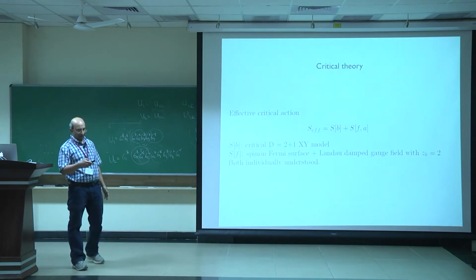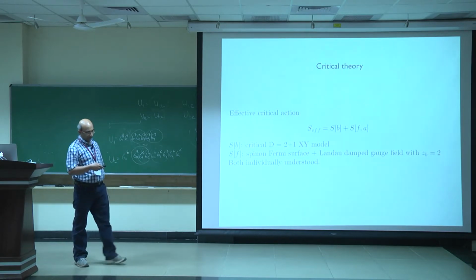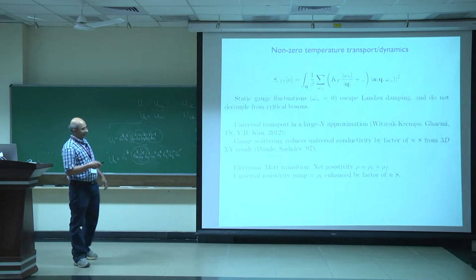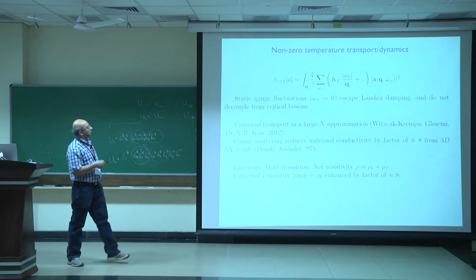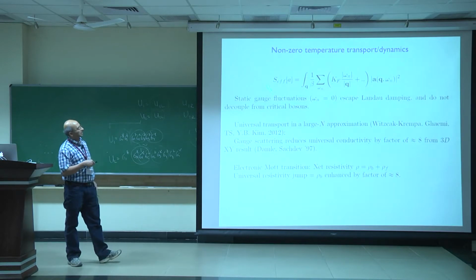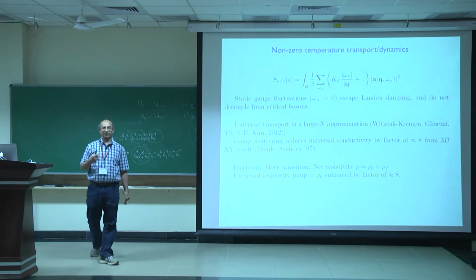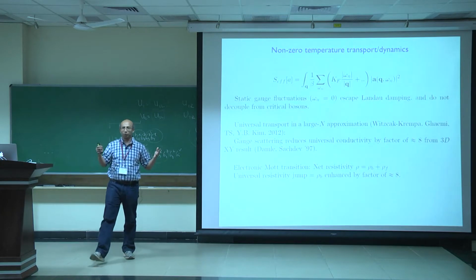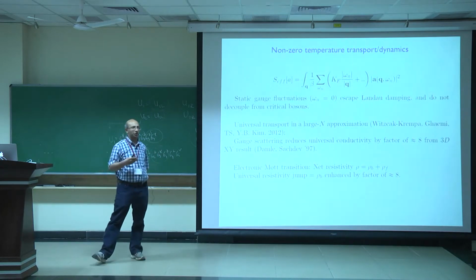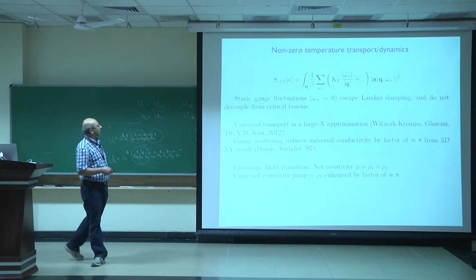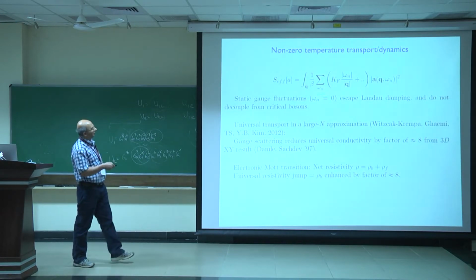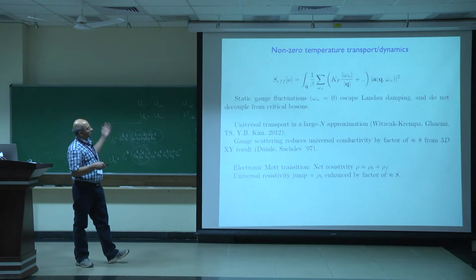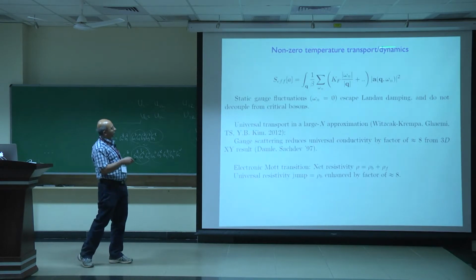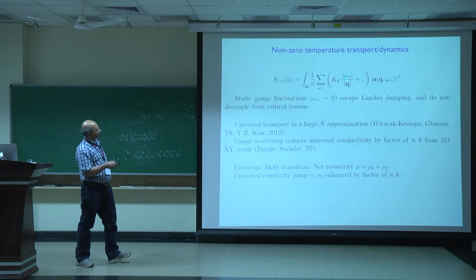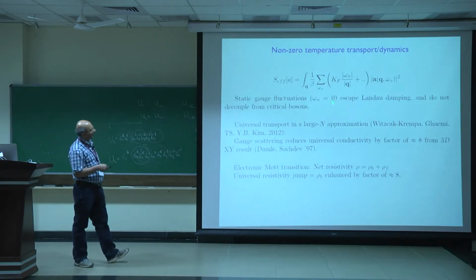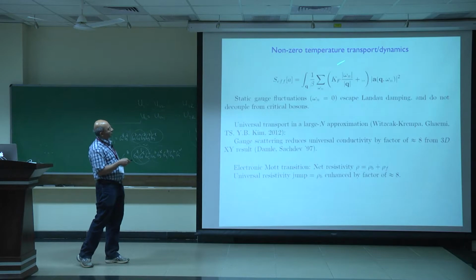There's a twist to the story which we realized only a few years back, only 2 years or so ago. If you're interested in non-zero temperature transport or dynamics, as we should be, if we want to go ahead in experiments and look for this prediction of this universal jump with the residual resistivity or things of that sort, then we have to revisit the logic that I just described at non-zero temperature, and then all these frequencies become Matsubara frequencies. And then there's a curious phenomenon.